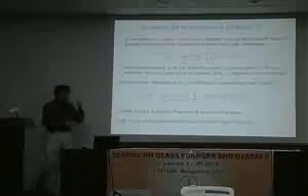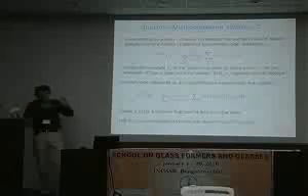Now, this is bad news, because instead of measuring nu square partial structure factors, they just get a weighted sum of these quantities. However, the good news is that these neutron scattering cross-sections depend on the isotope. And so what you can do, for example, is take the same sample, but replace one of the elements with another isotope of the same element.